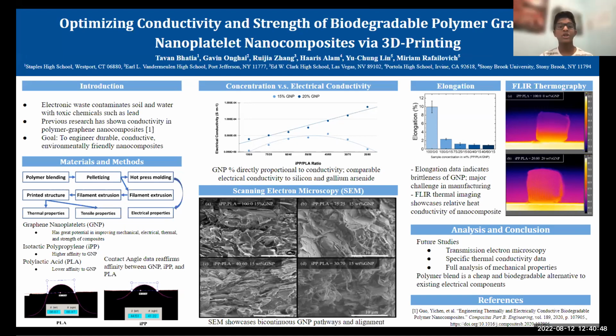There was a direct proportionality observed between the graphene and conductivity, which was comparable to silicon and gallium arsenide, essential components of semiconductors. We noticed a direct trade-off between efficiency and durability with increasing graphene, which is definitely something that needs to be considered for manufacturing. Our future work consists of a full analysis of mechanical properties, specific thermal conductivity values, and transmission electron microscopy to explore IPP domains, as well as the general testing of more samples.